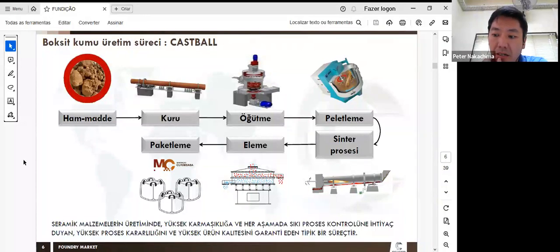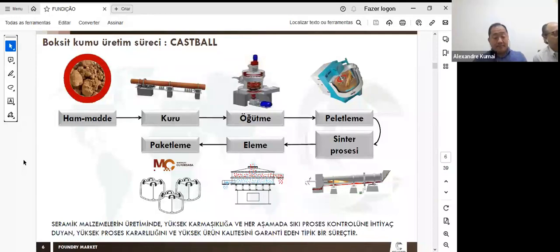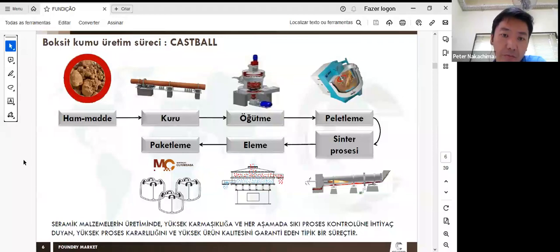After the raw material is prepared and all analyzed, we start the drying process. Drying is done in these rotary dryers, in which the capacity can go over 1,000 metric tons per day. In this process, we have to reduce the moisture from the bauxite from 25% to less than 5%. After drying, we have to mill the bauxite. So here we use the pendular mills to produce a powder of the bauxite. This powder of bauxite has a particle size of more than 90% less than 45 microns. So it's a very fine powder that we have to produce here during milling.